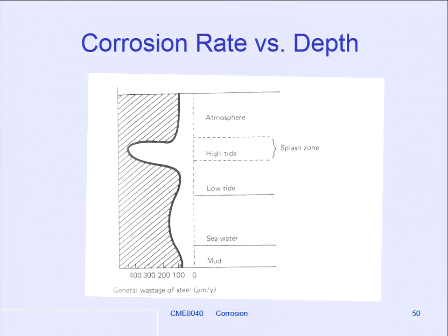As you get lower down in the seawater, the oxygen concentration is falling slightly, and the magnitude of any differences, because we're looking for oxygen differential, gets smaller. And so the bulk of the corrosion, this is corrosion rate in microns, 10 to the minus 6 per year, the bulk of the corrosion occurs near the surface because of that interface between a high oxygen area and a low oxygen area. So it's oxygen differential that drives the corrosion processes.